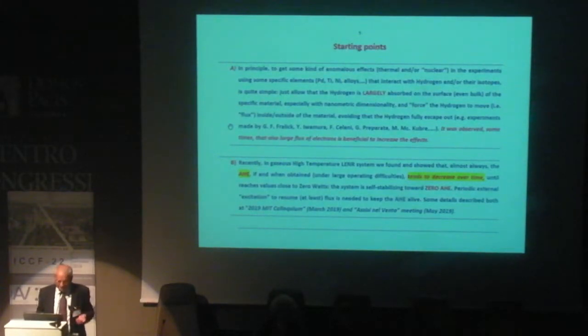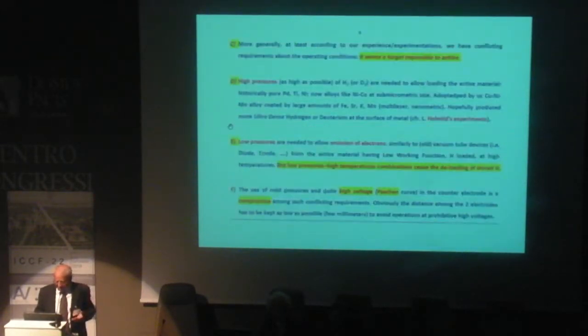Moreover, we observed, not only us, that some flux of electrons can help the effect. The main drawback, at least in our experiments, from a long time, is that at the beginning, when you make some change, you have a normal heat. Later, almost always, all excess heat goes to zero. So it means the equilibrium condition is zero power equilibrium. You have to make non-equilibrium. And so the problem is we want something useful. We need continuous excitation. We need flux or something more, or damaging of material, something difficult to identify in some way.